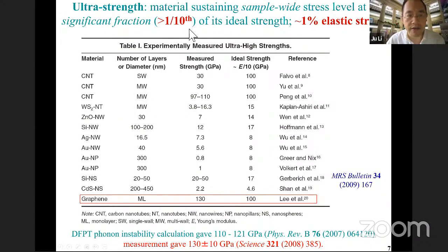And so we define ultra strength as a component that sustains a component-level stress which is more than 10% of its ideal strength. And ideal strength typically is on the order of 10% of the Young's or shear modulus. This column is from density functional theory, what the ideal strength of the lattice should be. And 10% of this is basically about 1% elastic strain. So if you have a material which can, at the whole component level, sustain 1% elastic strain for a very long time, like a few years, then we call that ultra strength.